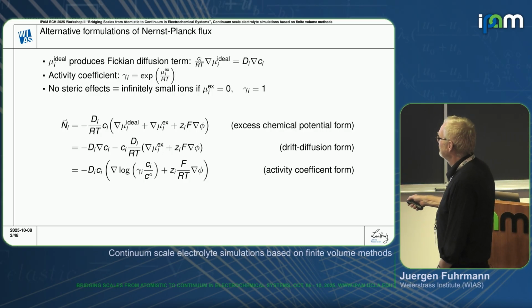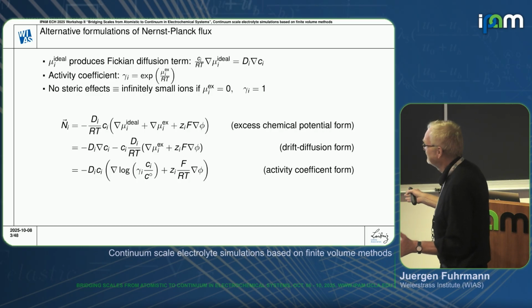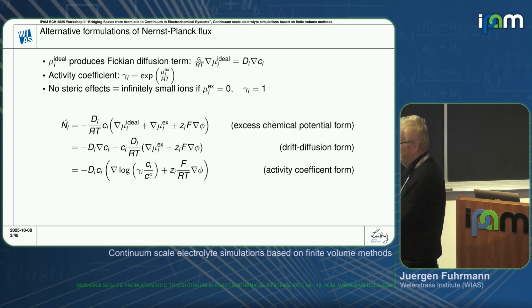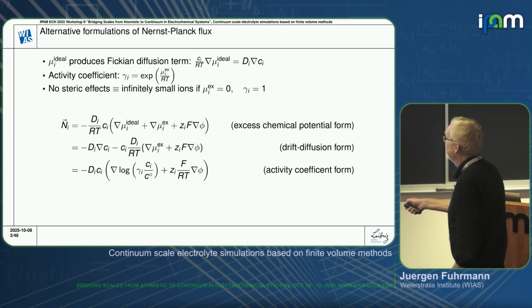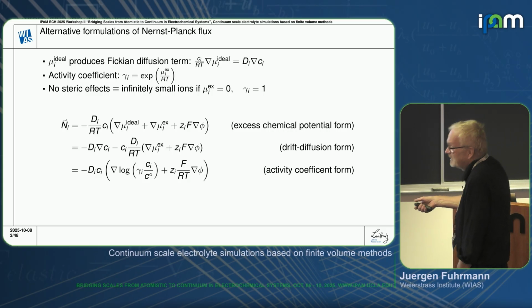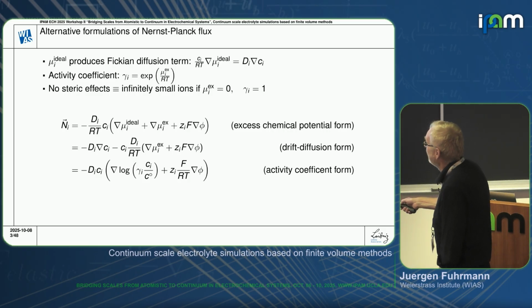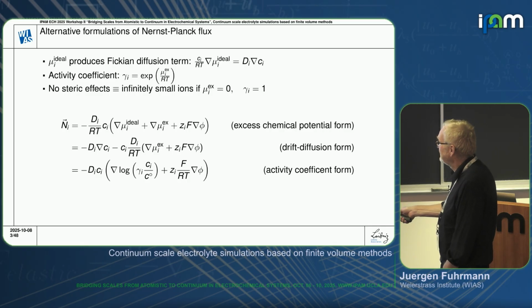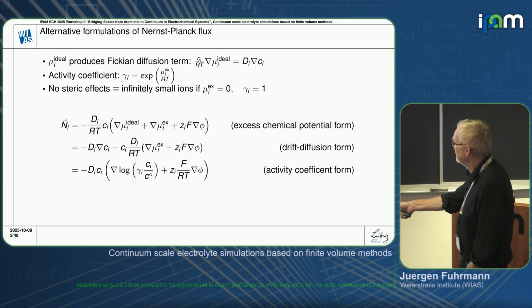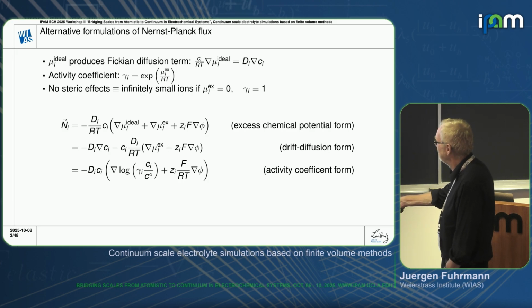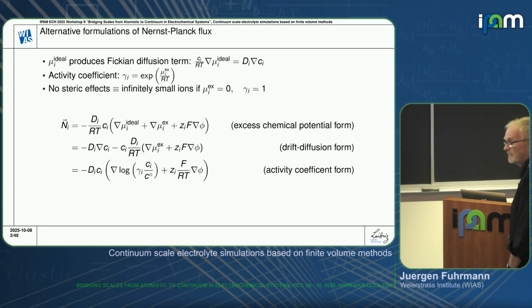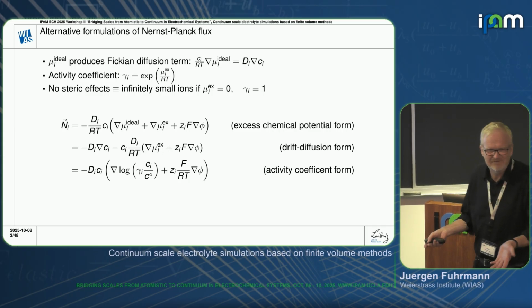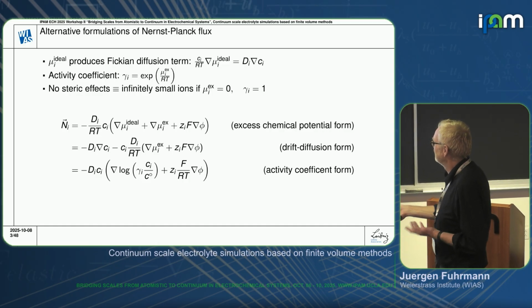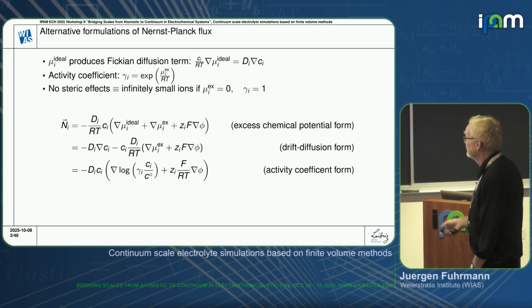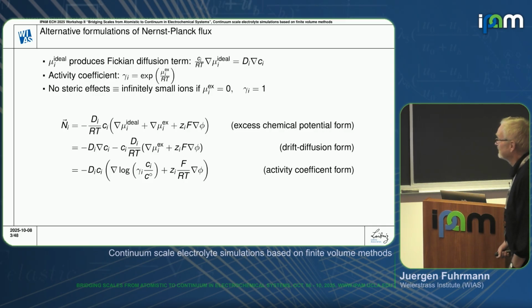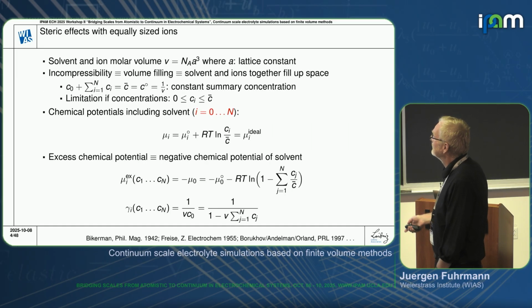There are different sub-languages in this field. Some people talk about excess chemical potentials, others talk about activity coefficients. In this context, the activity coefficient is the exponential of the excess chemical potential. Once we have it, we can also write the very same Nernst-Planck flux in this form, where we write the logarithm of the activity coefficient times the molar fractions. For instance, Stefan Ringe writes Nernst-Planck fluxes in this way, so you have different possibilities here. And as I said, this gives rise to different ways to treat them mathematically.